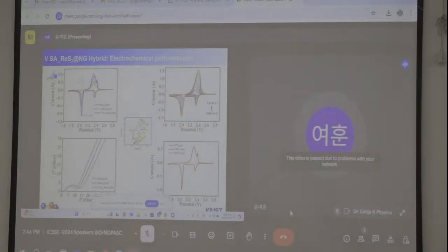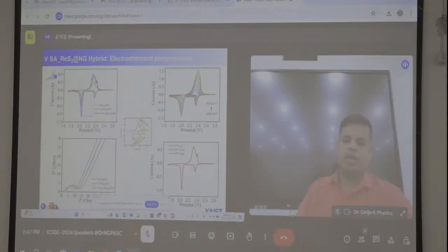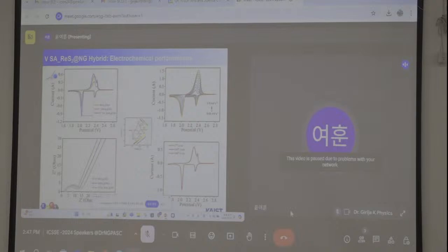This is the RS value. This is the ion transportation. Usually this is the high frequency, and this is the low frequency, which is from the ion transportation. This is the RCT value we calculate from here. But in the case of our optimal single atom decorated catalyst, there is a lower RCT and high ion transport behavior.